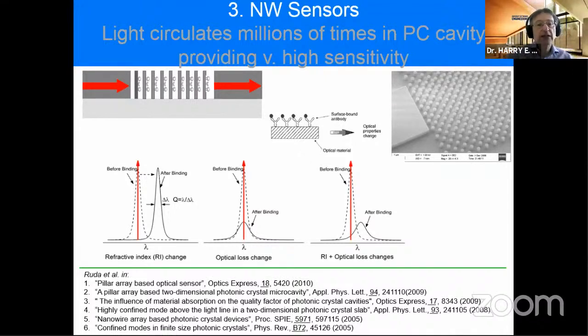And why do we want a cavity structure? Well, because if we're trying to detect very, very low concentrations of analytes, then in a cavity the light lasts a long time. It bounces around many, many cycles, and so it keeps on sampling the same low concentration, and so we effectively have a higher concentration. And there are two ways in which the binding of, for example, a biomolecule on the surface of the structure would change the optical response.